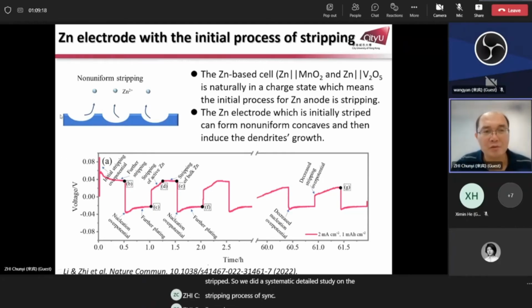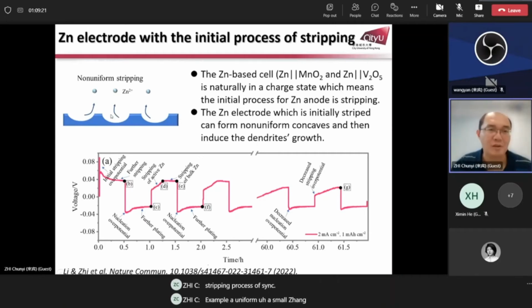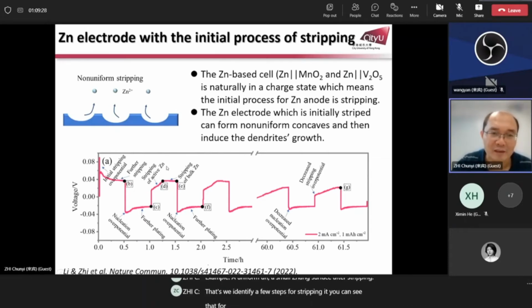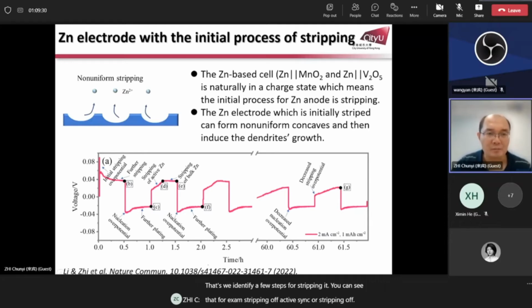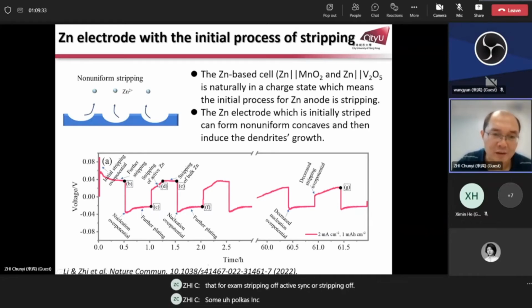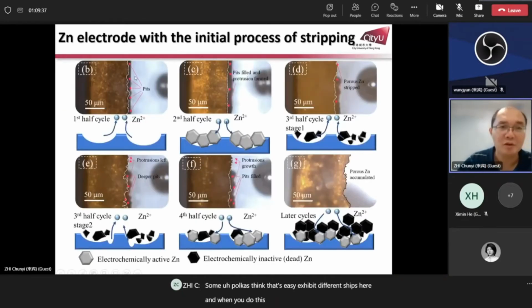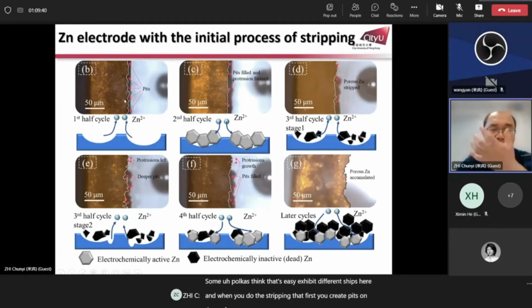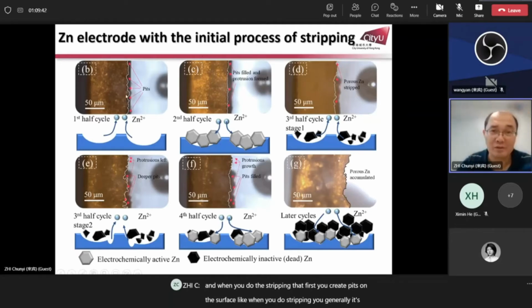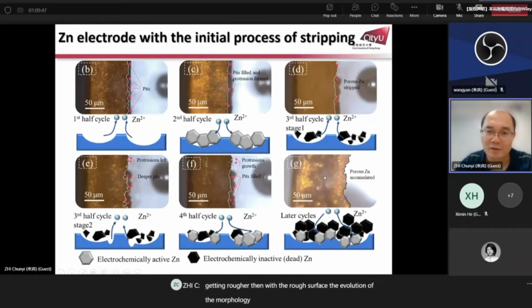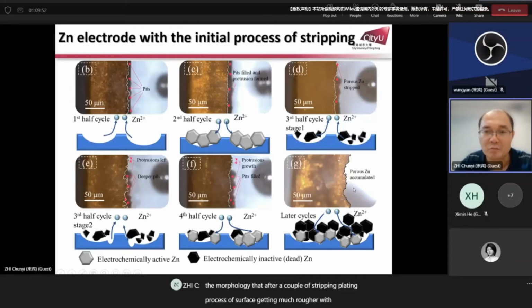For example, for a uniform, smooth zinc surface after stripping, we identified a few steps for stripping. You can see that, for example, stripping of active zinc or stripping of some bulk zinc exhibit different shapes here. When you do the stripping, first you create pits on the surface. Generally it's getting rougher. Then with this rough surface, the evolution of the morphology after a couple of stripping and plating processes, the surface gets much rougher with porous zinc accumulated.